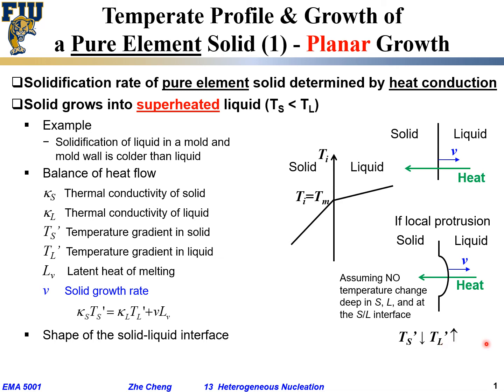On the other side of the interface, you would make the same argument. The temperature at the interface does not change, maintained at T_M. Deep within the liquid, the temperature also does not change. But because of the local protrusion, the local distance over the protrusion in the liquid phase gets smaller. Delta T is the same. Delta X, the distance, gets smaller, which means the temperature gradient gets larger. Okay? So you see, T'_S gets smaller, T'_L gets larger. On the left side, T'_S gets smaller, K, the thermal conductivity, does not change. On the right side, T'_L gets larger, kappa_L does not change. So the left side gets smaller, and on the right side one term gets larger.